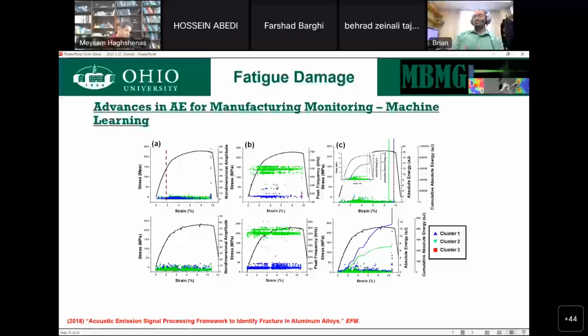So the clustering may not have been the most accurate to identify every last source. But what we do know for sure is that your green cluster is more likely to be some kind of damage than the blue cluster is. It's not to say the blue cluster doesn't contain some level of damage, but it's less likely to contain the damage because it has significant frequency content in the same range as the operating machinery itself.